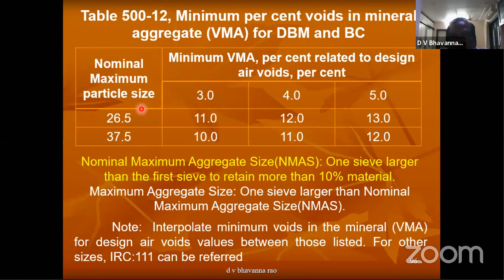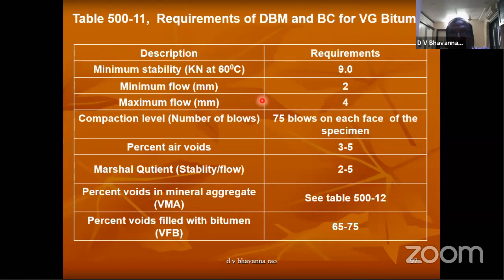From this table, we can find out the voids in mineral aggregates for a DBM. And the design requirements of DBM and BC: you find the minimum stability value 9, similar to compressive strength. Minimum flow value, maximum flow value 2 to 4. It indicates the workability of the bituminous mix.